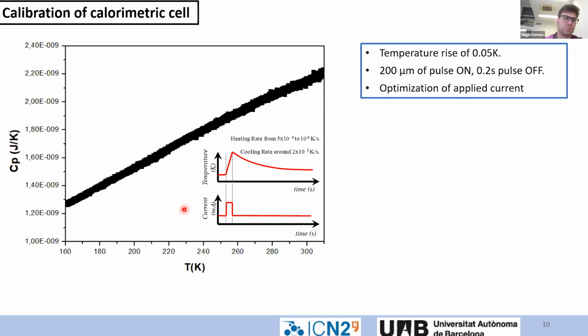The first thing we have to do in order to measure the heat capacity is calibrate the calorimetric cell. How do we do it? We simply start at a lower temperature, taking the range of temperatures that we want, and we start to raise it in a controlled way. We do it at around 50 millikelvin steps, using pulses in the range of microseconds, and then we let the calorimetric cell cool down so that the reference temperature is the same at every single measurement. We get this heat capacity of our calorimetric cell compared with our temperature.